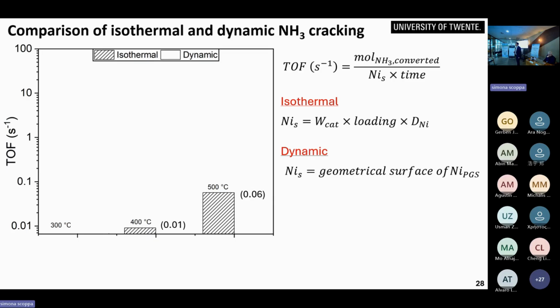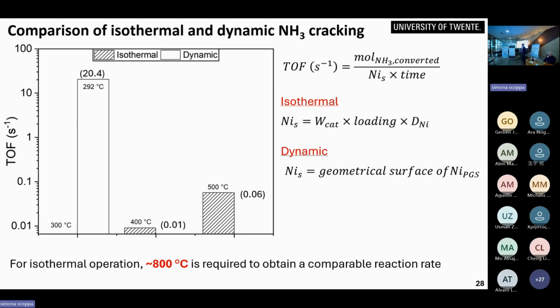Now, when we look at our material, this is the turnover frequency that we get. We get about 20 seconds to the -1 at 292 degrees C, and that resembles the activity of a nickel-based catalyst at 800 degrees C. So this is a unique way of activating the nitrogen molecules, in this case the ammonia molecules, at a much lower average temperature.